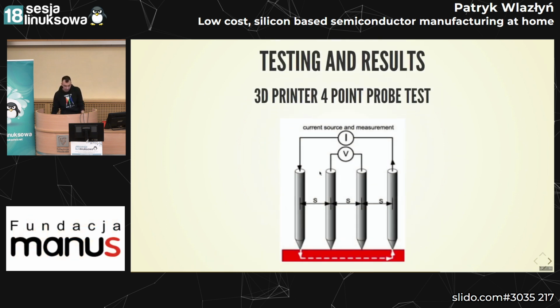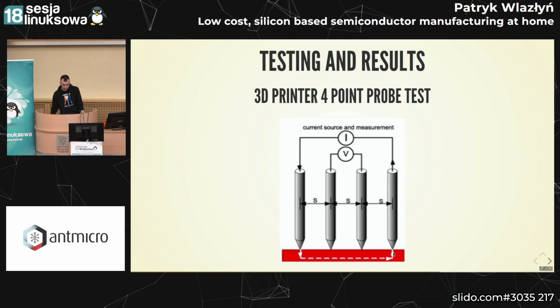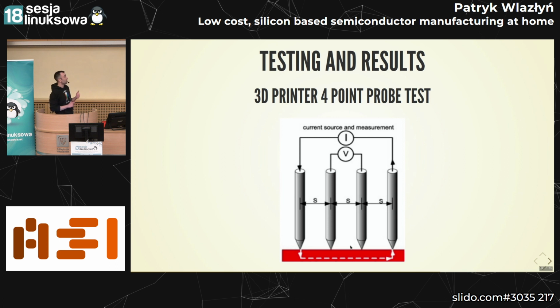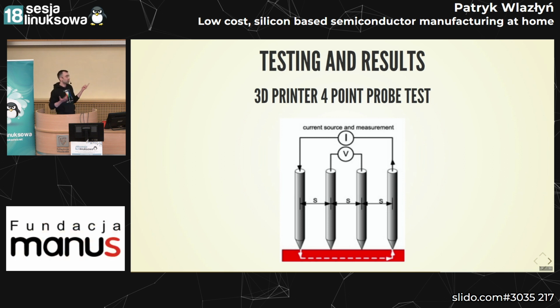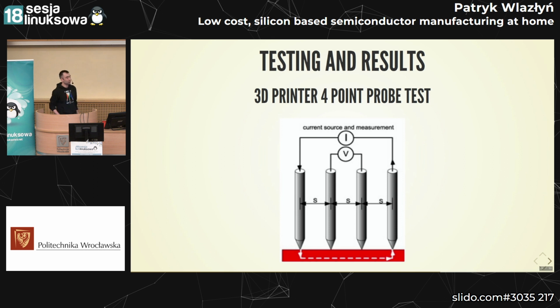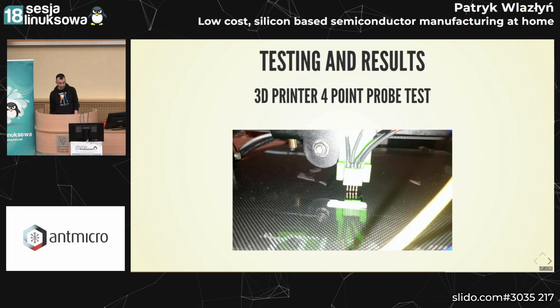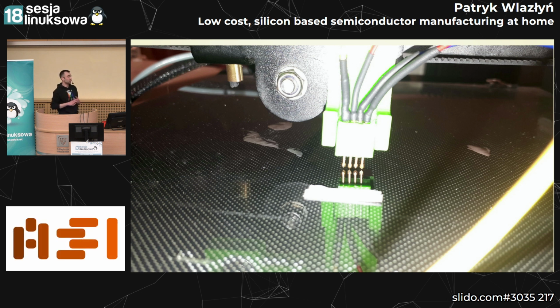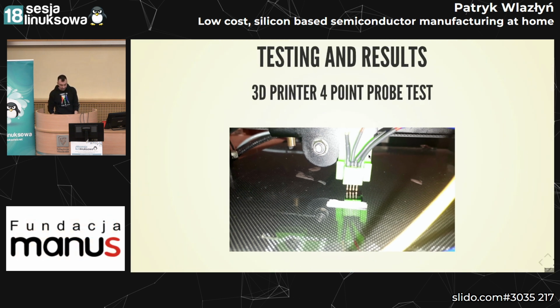Another way of testing the wafer is using a 4-point probe test. You apply a constant current on the outer probes of the 4-point probe, and you measure the voltage in between. When you know what current you were flowing and what voltage was measured, you can determine the resistivity, and from the resistivity you can derive how well you doped the wafer in this place. And we had a 3D printer set up for it. We had 4 probes connected to the 3D printer that was going over the wafer, measuring for each place on the wafer how well it was doped by measuring this resistivity. But in practice, it actually doesn't work that well.